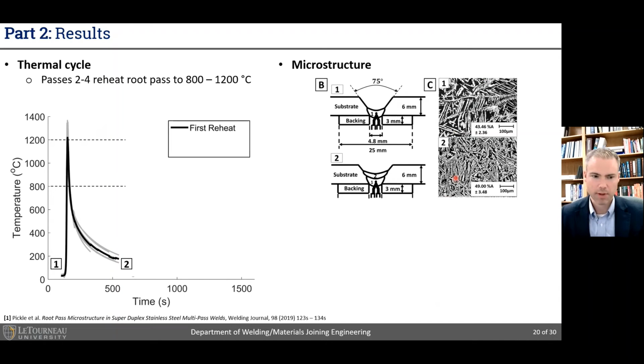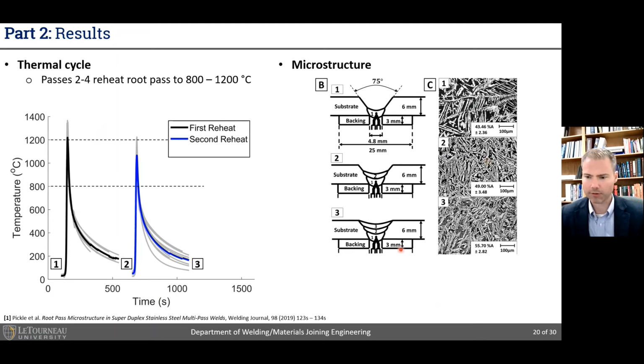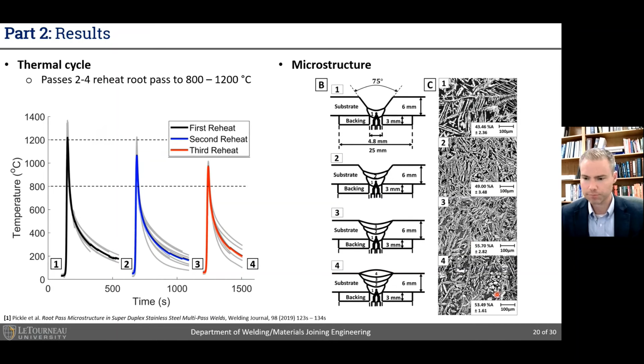As we add the next pass, you can see the thermal cycle here. We find a peak temperature of roughly 1200 degrees C, and we can see that the austenite volume fraction increases. So we've now terminated the experiment, sectioned this weld, and now we're measuring the austenite volume fraction here. Continue the experiment, do the same thing. We find the austenite volume fraction increases again. And then finally, we do the final and find that within the uncertainty, it's about the same, or perhaps it's decreased just a little bit. All of these passes have peak temperatures between 800 and 1200 degrees C, which is the range in which it's known to drive secondary austenite formation. So this all seems quite telling.